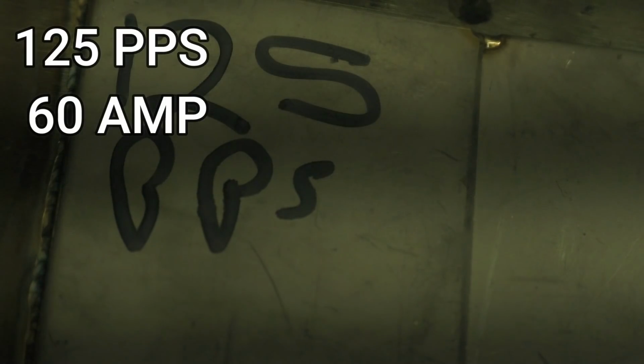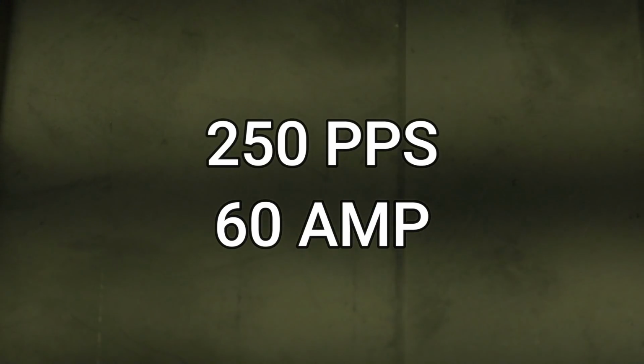This is the same material, the same weld, except I'm going to weld this one at 125 pulses a second. That's the only thing I'm changing, just the pulse frequency. Still welding on full pedal, full amperage. This time it's turned up to 250 pulses per second. You can see straight away it's a much tighter, hotter arc. It really is nice to weld with.